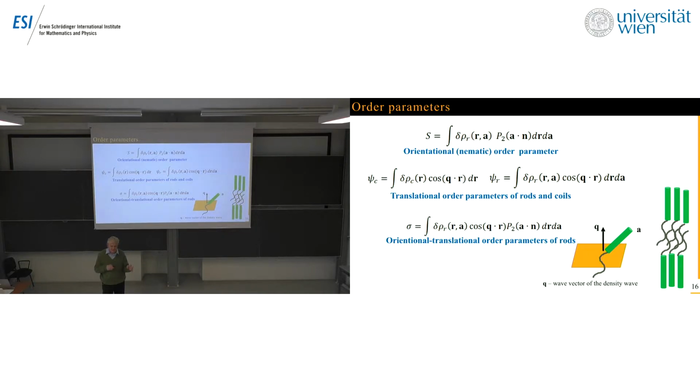In the case of polymers, this is quite important because, due to the microphase separation, we have an orientational density wave, which normally appears. In particular, when there is no nematic phase, when the system goes directly from the isotropic phase into the lamella, then two types of order appear simultaneously. As a result, this is a very important order parameter here.